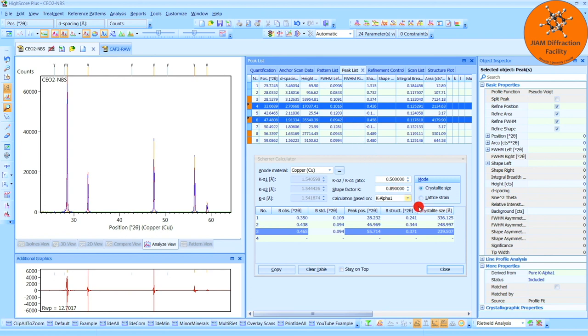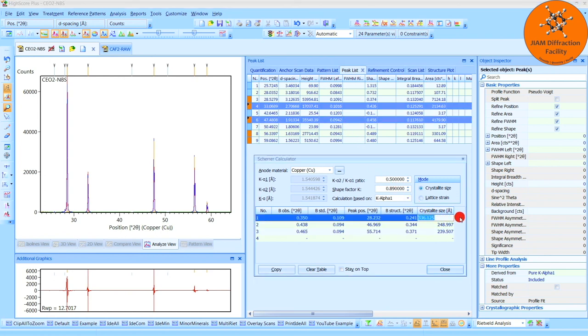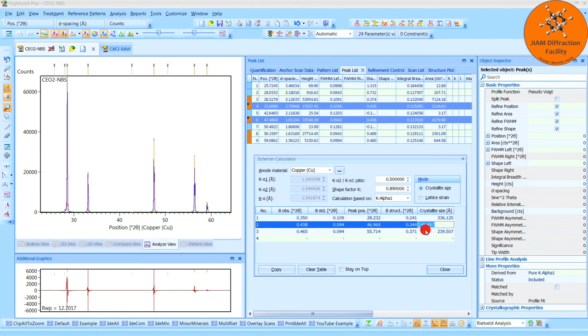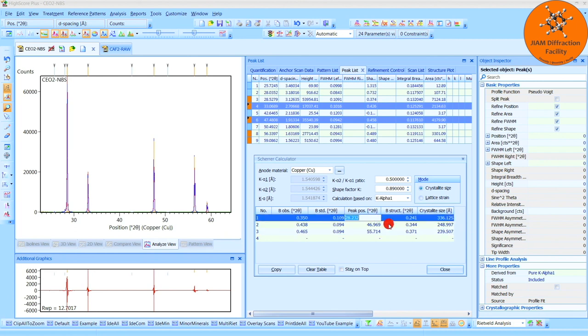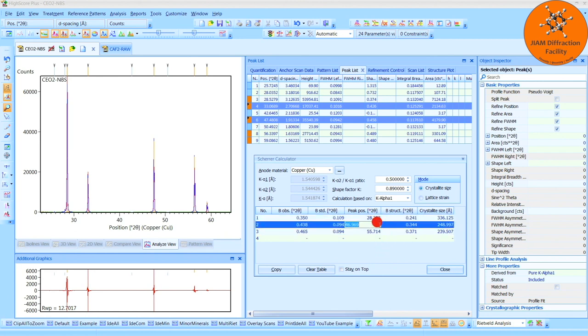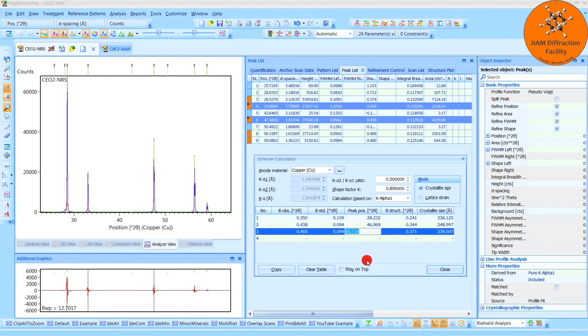But let's go ahead and look at the results now. We see that the crystallite size for the first peak is 336, for the second peak it's 249, and for the third peak it's 239. So the crystallite size drops greatly from that first peak down to the next two, and the next two are pretty similar. And you'll notice that this one falls below that 30 degree mark and this one falls right in that 30 to 50 degree range. This one's a little bit farther out of the range, but we still seem to get pretty similar results from the second peak. So for this analysis I would state that the crystallite size is probably around 249, maybe somewhere between these two, we'll say 245 angstroms.